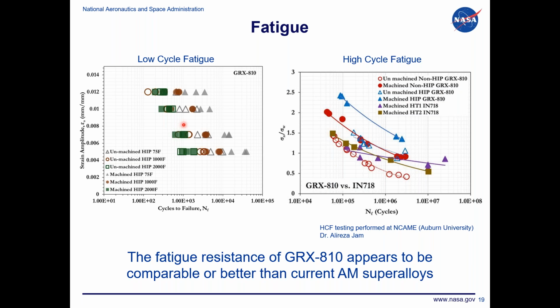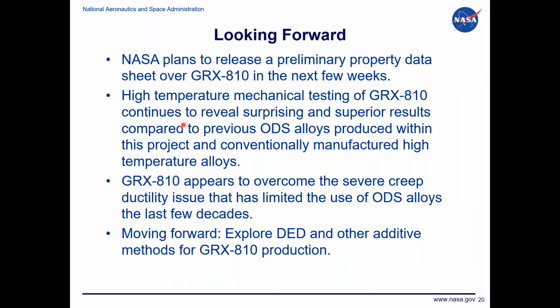And so in some instances, like high cycle fatigue here on the right, we're comparable, or if not even a little bit better than, let's say, 718. And we've done low cycle fatigue up to 2,000 degrees Fahrenheit, and it's done really well. So at least for fatigue, again, comparable, maybe better than other conventional AM superalloys. So that was my quick update.